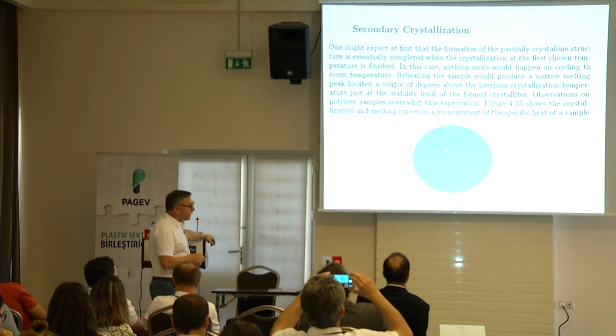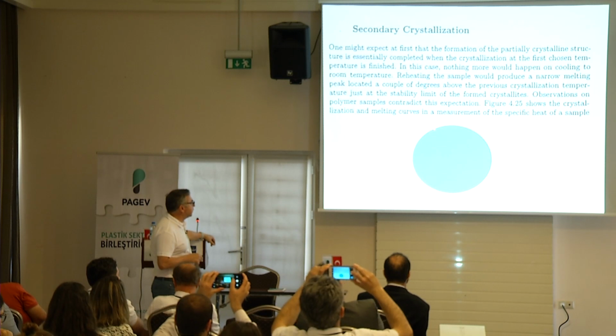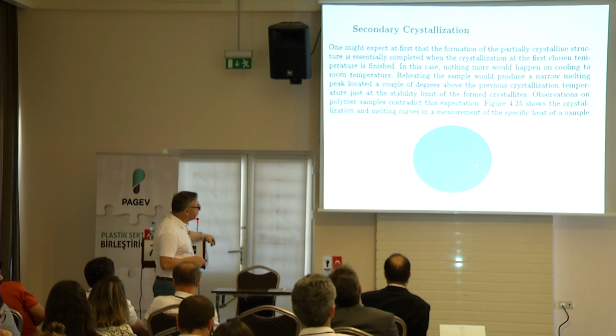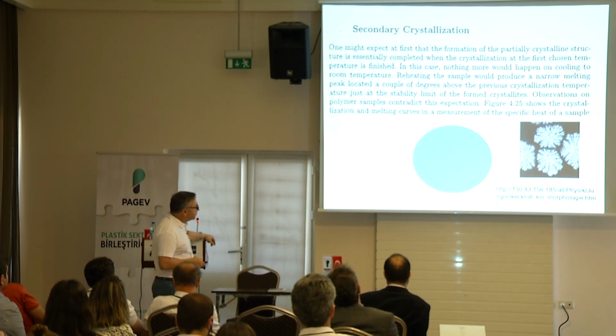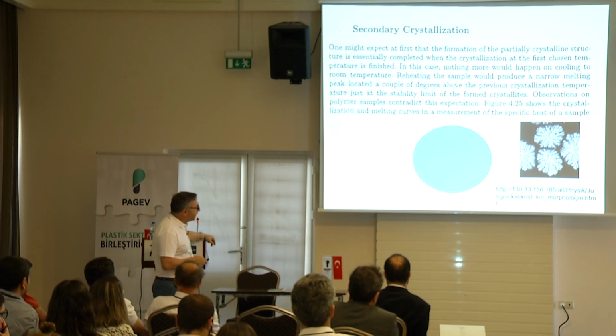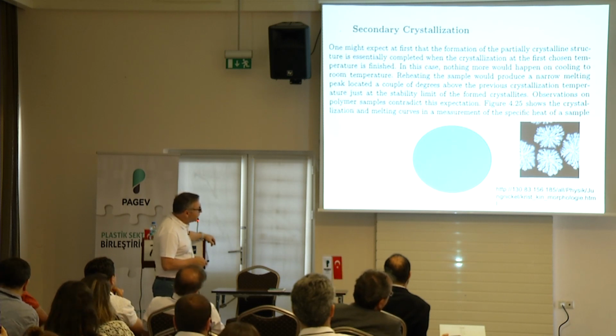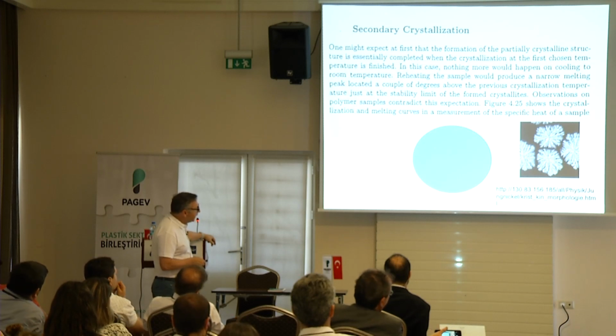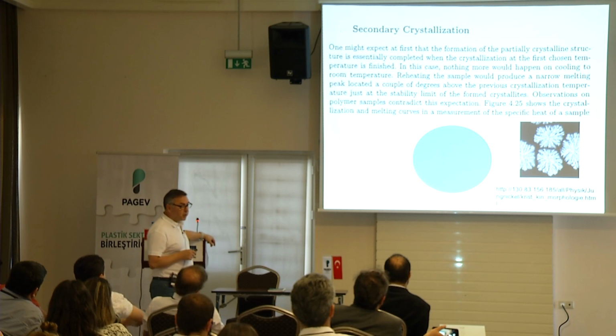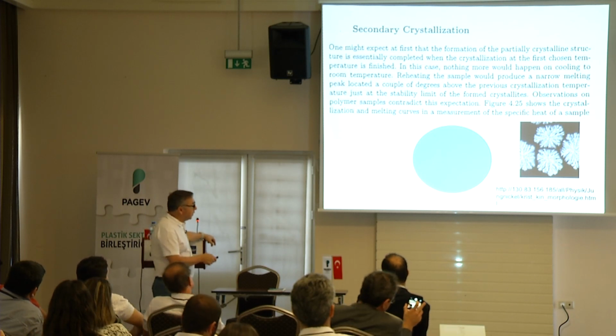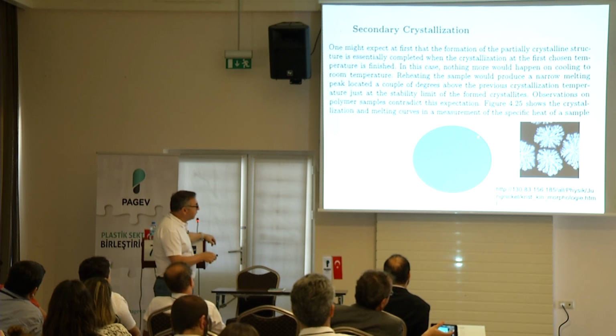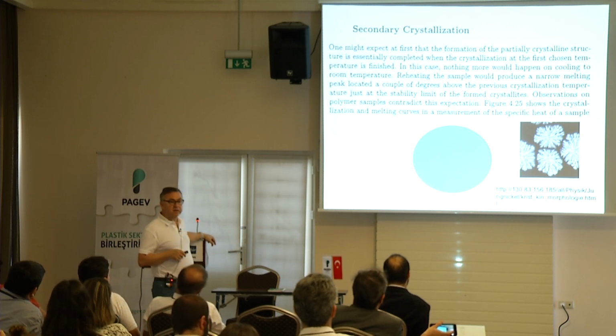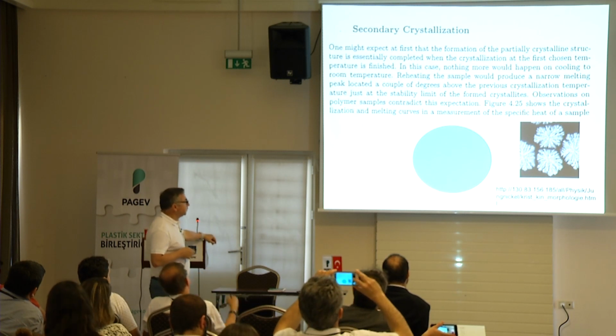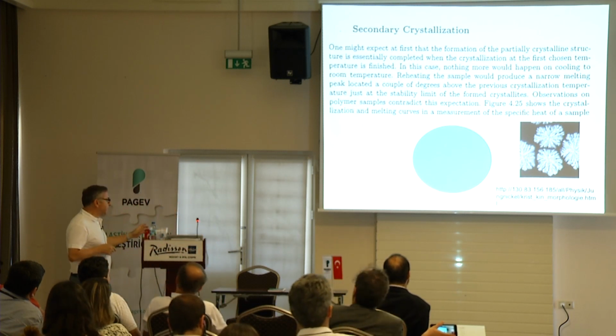So secondary crystallization, I want to revisit again. I want to make sure it registers with you that when the crystal grows, the volume inside is not completely converted. It converts later. And you see that this is even an exaggerated example of dendritic structure. All the black regions in between are unconverted, and they convert later. So this is a very important understanding of the material. Even though you measure the growth rate, it's only the growth rate of some partially converted crystal structure, not fully. Keep that in mind. The polymers are different.